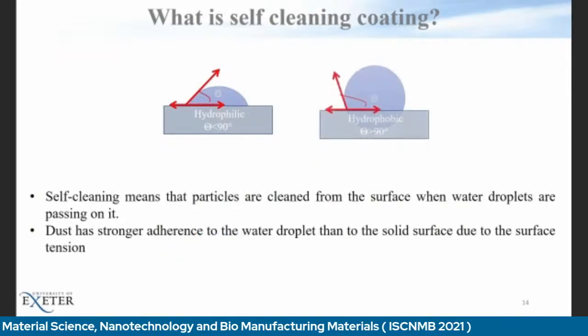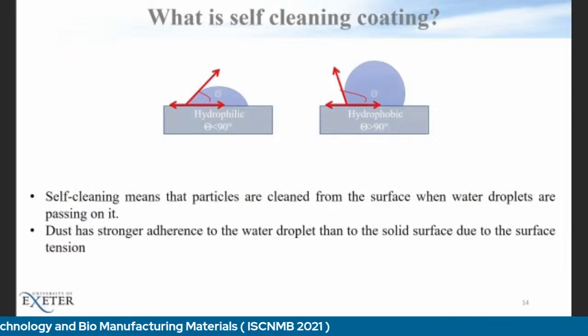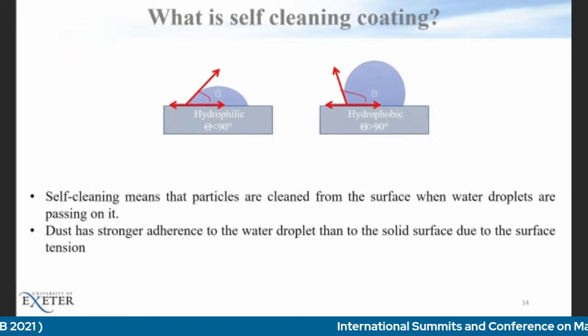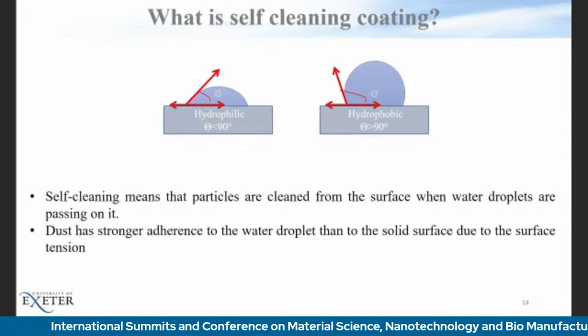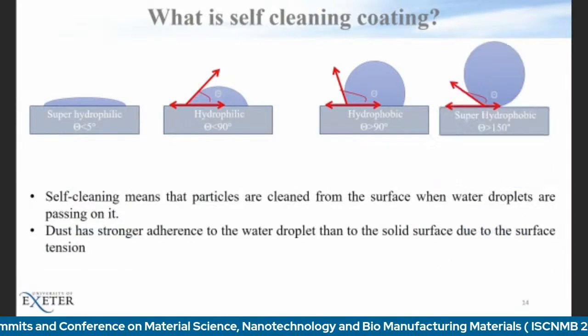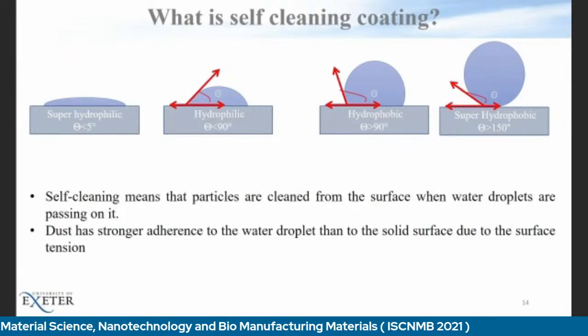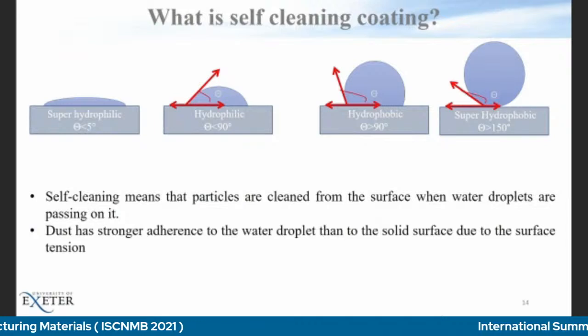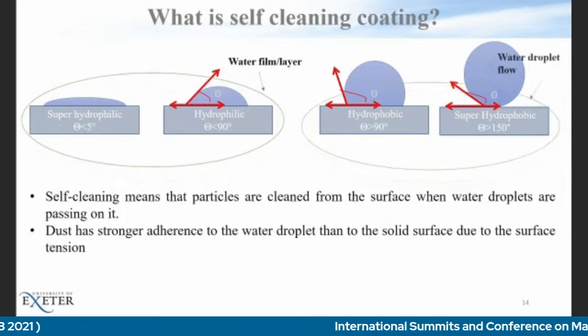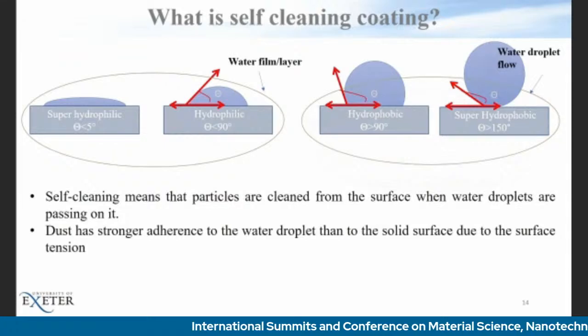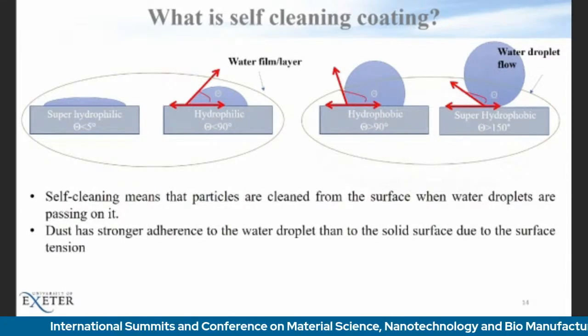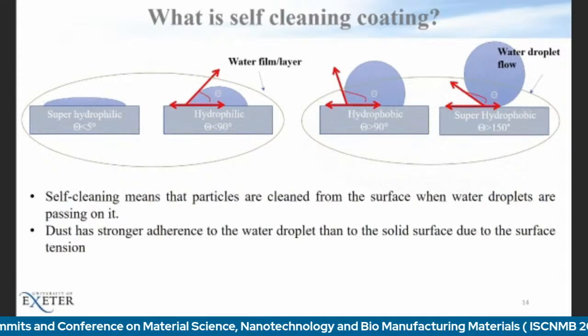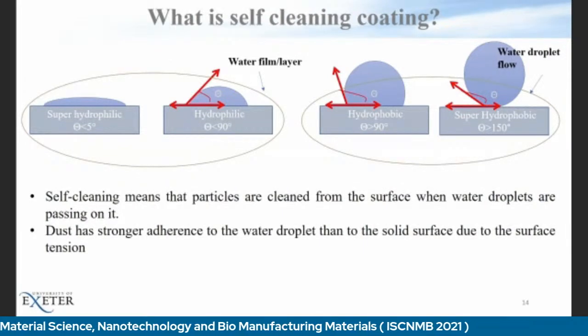Generally there are two types: one is the hydrophilic coating, one is the hydrophobic coating. Because of the different contact angles they create on the glass surfaces, it is called hydrophilic when the water contact angle is less than 90 degrees, and when the contact angle is over 90, it is called hydrophobic. There are two other categories, superhydrophilic and superhydrophobic. When the water contact angle is above 150, it is called superhydrophobic, and when it is less than 5 degrees, it is called superhydrophilic. These are all very crucial, and if you want to create a coating material, you have to find out whether it is superhydrophilic, hydrophilic, hydrophobic, or superhydrophobic.